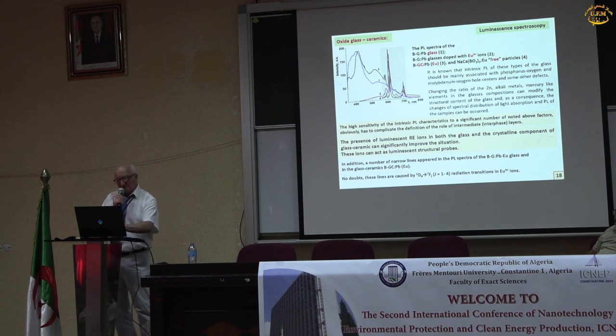So here you see the luminescence of various objects. This is a glass. They show a wide band luminescence. You see the luminescence of glass doped with europium 3+ ion probes. And we see also the luminescence of powders that contain luminescence active europium 3+ ions.